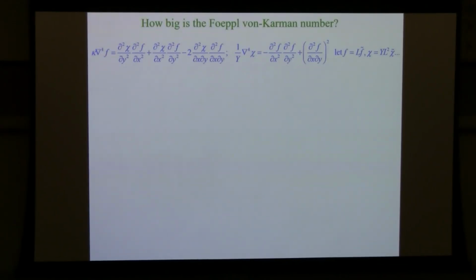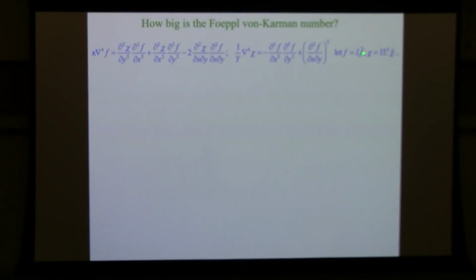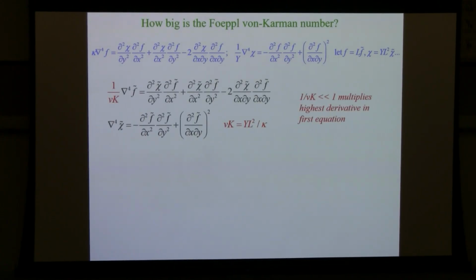You can see that on this next slide here. I'm just repeating the Foeppl-von Karman equations. And the crucial thing about them is that this bending rigidity, which is typically rather small, for graphene, it turns out in some appropriate units, it's really, really tiny. It multiplies the highest derivative in the problem. And 1 over the Young's modulus, which is typically gigantic for something like graphene, its reciprocal multiplies the highest derivative in the problem. And if you just scale out the overall size and the Young's modulus and the bending rigidity in the appropriate way, what you get are these dimensionless Foeppl-von Karman equations. And here is this single dimensionless parameter, this combination, which is Young's modulus times system size squared divided by bending rigidity.